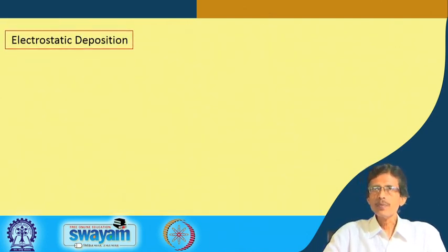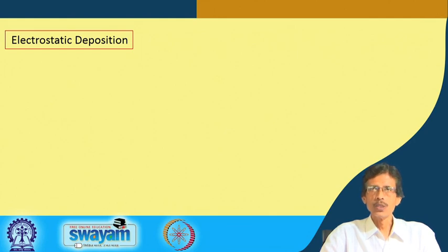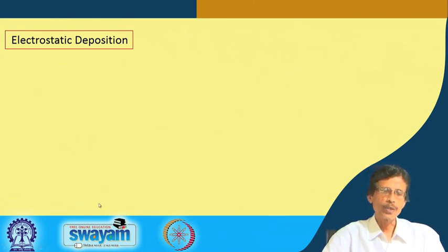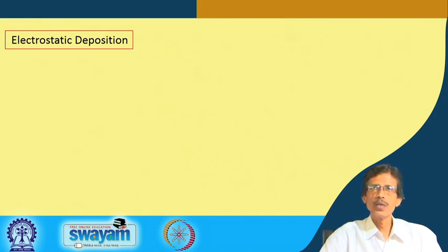Then another technique, other than this wet and dry application, is electrostatic deposition. If you have difficulty in applying through wet application and dry application, we can go for electrostatic deposition. So, we take charged particles. We have the particles in powder form like your talcum powder, but now we apply some electric charge such that the particles are charged. If the substrate or the container is oppositely charged, that will attract those charged particles, and uniformly, through that corresponding charge uniformity on the surface, the deposition of those charged particles will take place under electrostatic control.